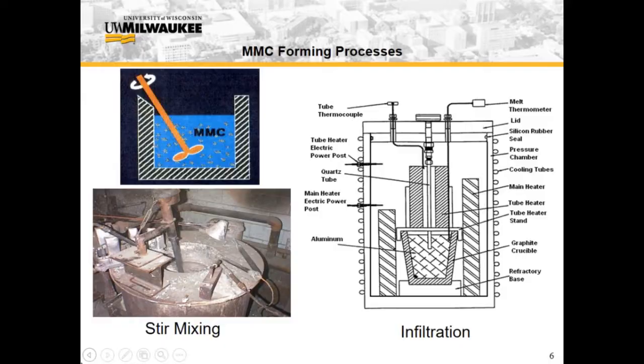Schematically, what you do in stir mixing, you produce a melt like you do in any foundry, and you use a stirrer to mix particles or short fibers in the melt, and then you pour this suspension in the mold to produce a casting. Here is an example of our industry partners where they are melting 400 pounds of aluminum, and this is the mixer, and they will add particles to create a metal matrix composite melt which can be poured into the casting.